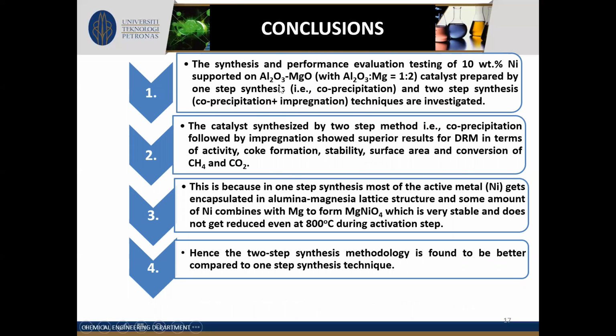Coming finally to the conclusion, we can see that the synthesis and performance evaluation testing of 10 weight percent nickel supported on alumina magnesia, with an alumina to magnesia ratio of 1:2, which is best as seen from the literature, has been prepared by one-step, that is co-precipitation, and two-step synthesis techniques. The catalyst synthesized by the two-step method, that is co-precipitation followed by impregnation, showed superior results for the dry reforming reaction, in terms of activity, coke formation, stability, surface area, and conversion of methane and carbon dioxide.